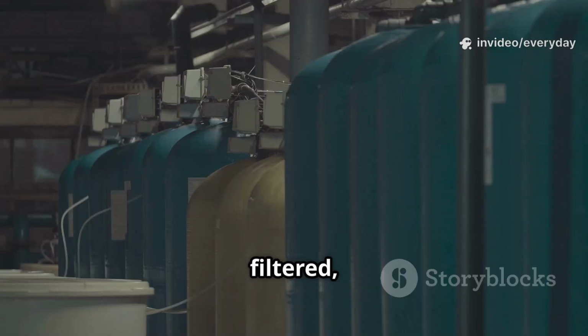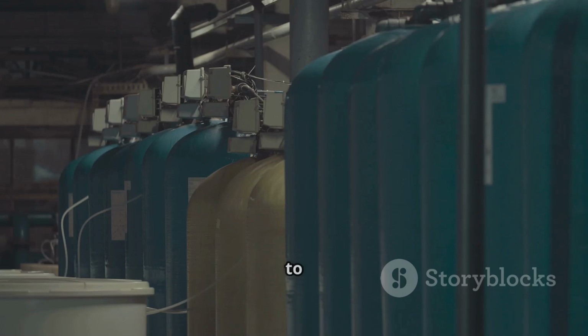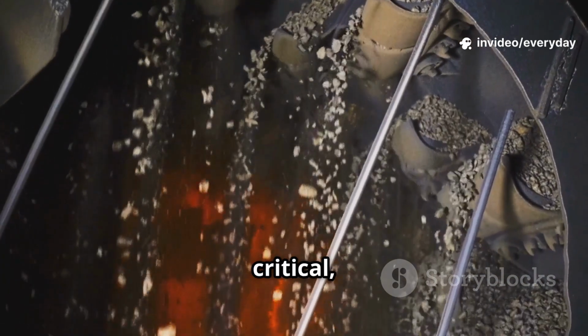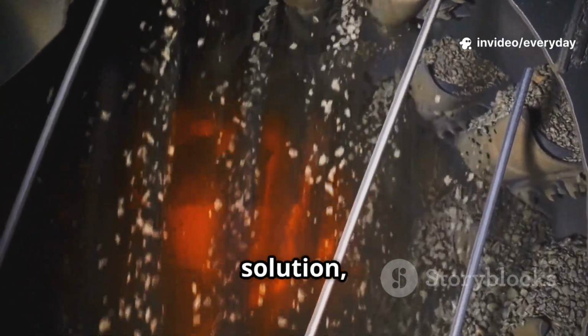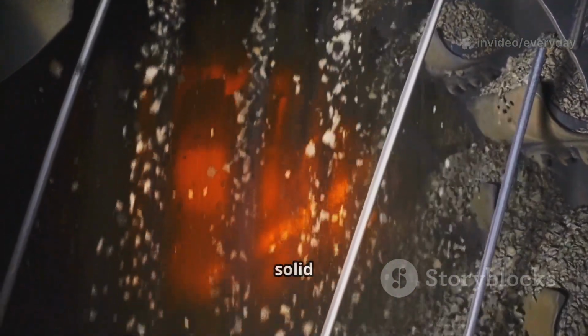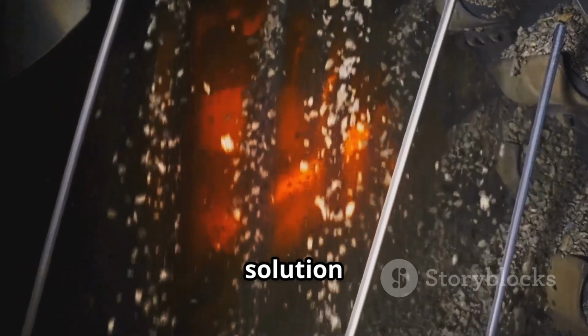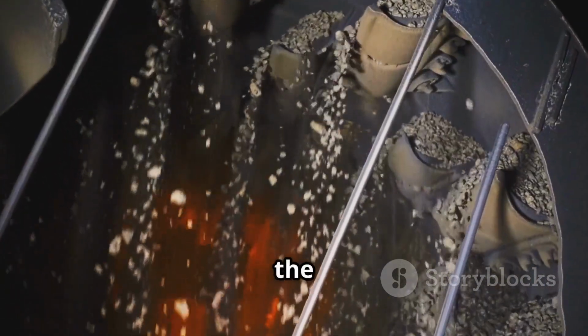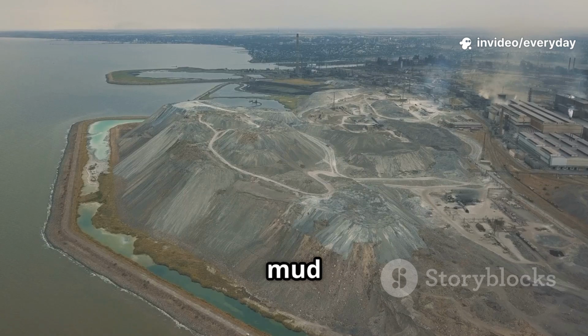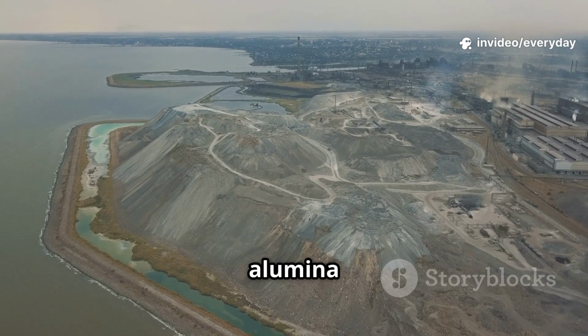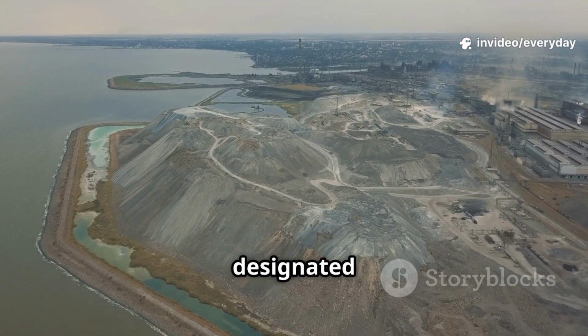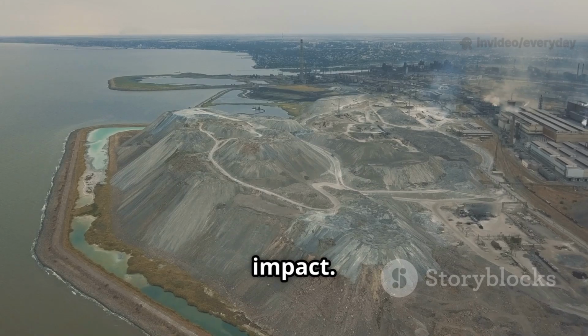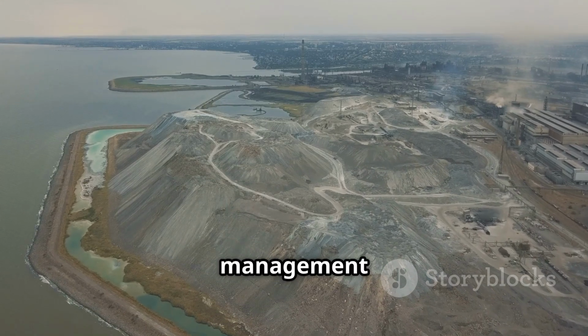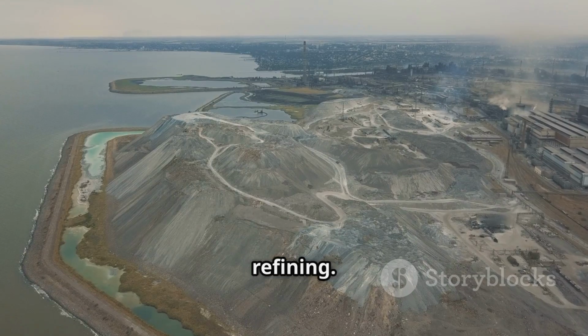The mixture is then filtered, using large-scale industrial filtration equipment. This step is essential to remove the solid red mud from the liquid alumina solution. This process is critical, separating the valuable alumina solution, now clear and purified, from the solid waste. The clarity of the solution is a testament to the effectiveness of the filtration process. The red mud is washed to recover any remaining alumina and then stored safely in designated ponds, minimizing environmental impact. Responsible waste management is a key priority in modern alumina refining.